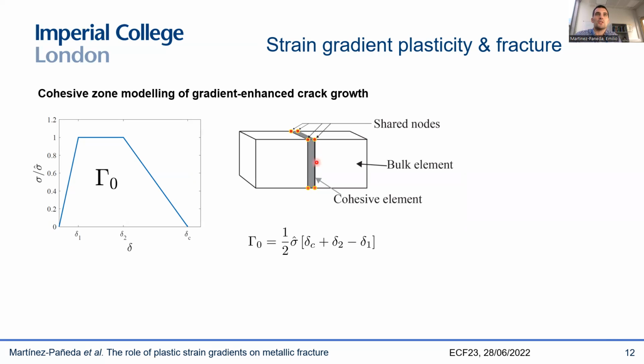So you basically place these cohesive elements along the crack propagation region, and these cohesive elements basically glue the two crack surfaces. And the behavior of this glue, of these cohesive elements, is governed by a traction separation law, like you see here, where the critical parameters are basically the area under the traction separation law, the fracture energy, the critical cohesive strength, so this sigma hat here, and then the shape of the traction separation law, which will give you this critical separation. And here we choose to follow Tvergaard and Hutchinson and use a trapezoidal traction separation law, which gives us this expression for the fracture energy as a function of the critical separation.